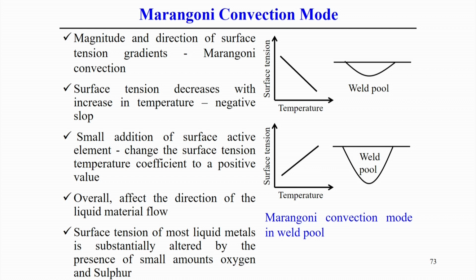So, that means surface tension decreases with increasing temperature. In the case of the welding process, exactly at the center point, the temperature becomes the maximum, and away from this center point, the temperature decreases. So, there exists a temperature gradient from the center to the outward periphery of the weld pool, and accordingly the surface tension also varies. The direction of the surface tension force depends on this variation of the temperature. That can be represented in this figure, where the gradient is a negative gradient.